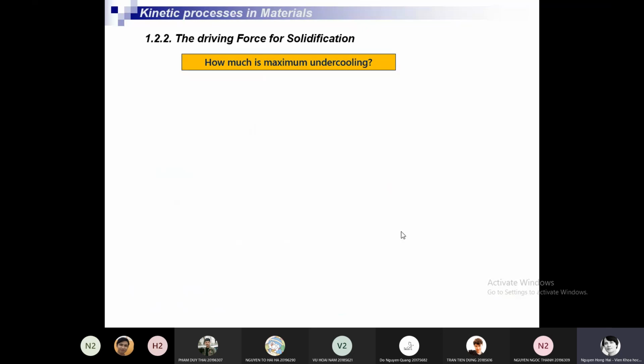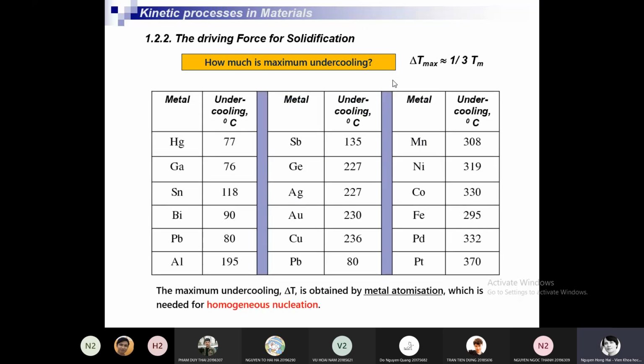So the question, how much is the maximum undercooling? In general, the maximum undercooling is 1/3 of the melting temperature. For different metals, you can have different values of undercooling. For example, for aluminum, the maximum undercooling is 195, for example. For iron, 295, and so on. For copper, 236.